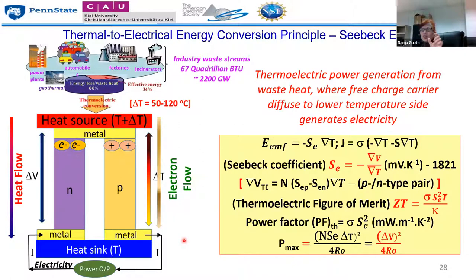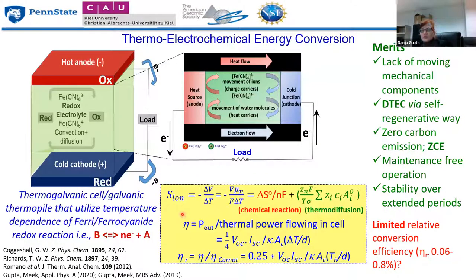So thermoelectrics are for the higher thermal sources or thermal loads. But here, what I want to show you is for low grade thermal energy harvesting, and it's not the classic Seebeck effect, but thermoelectrochemical energy harvesting. So once again, I'm utilizing electrochemistry for harvesting this low grade heat. The classic cell, what we call the galvanic cell, consists of a hot anode and a cold cathode, enclosed with the redox electrolyte. This is a mixture of ferro and ferricyanide.